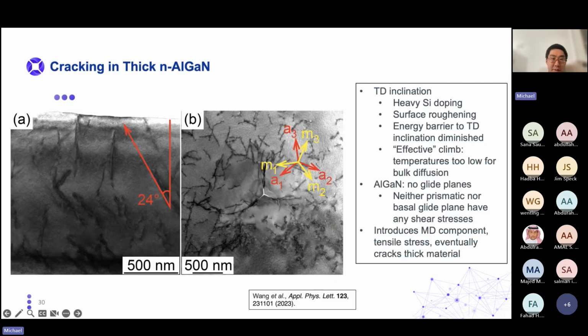So what's occurring here is that the threading dislocations in the material, these are the threading dislocation defects imaged through transmission electron microscopy, are inclining due to the heavy silicon doping that's required to get the very high conductivities that we desire for our devices. With this inclined dislocation, you can think of it as a pure thread component, which is vertical, and a misfit component. And the addition of these misfit dislocations throughout the entire material introduces stress in the n-type aluminum gallium nitride.